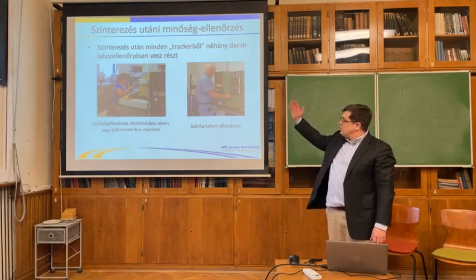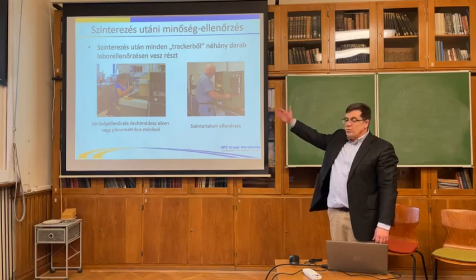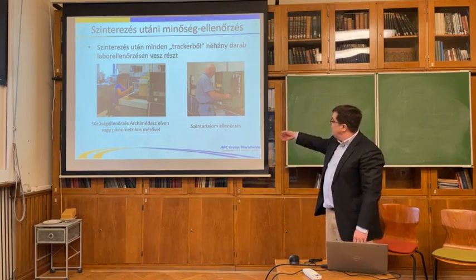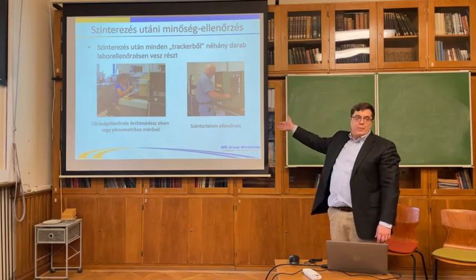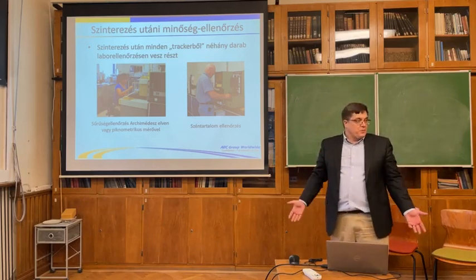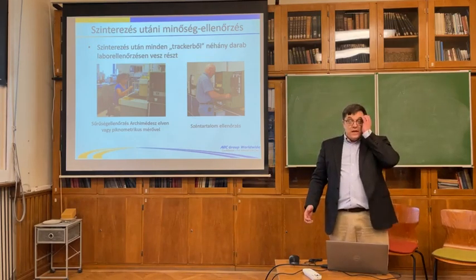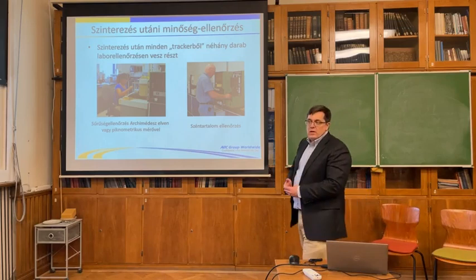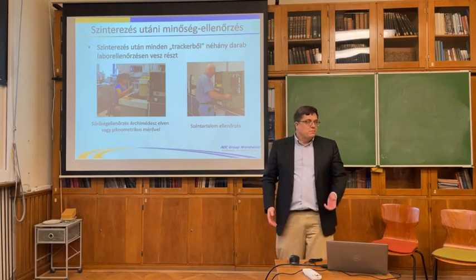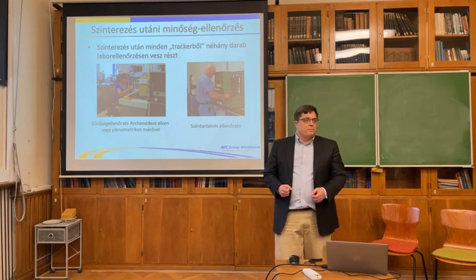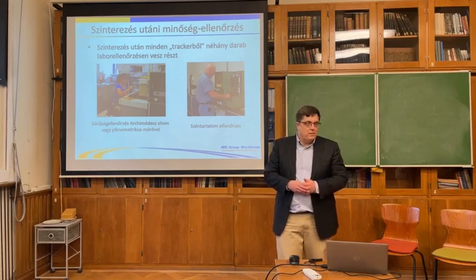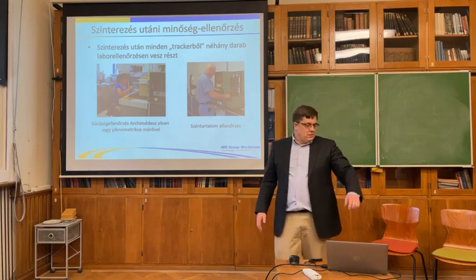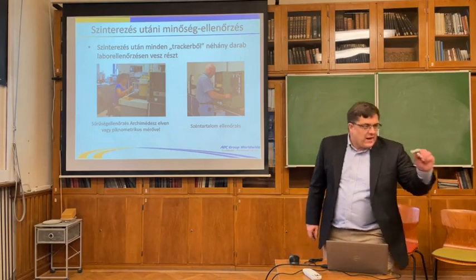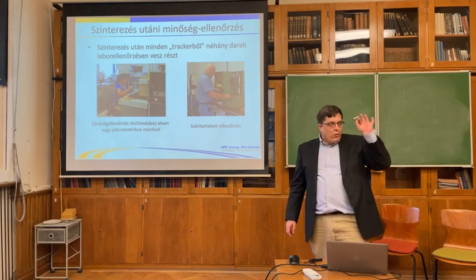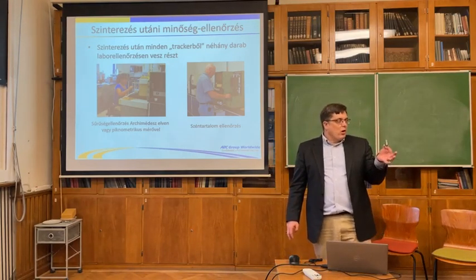So after the sintering, we measure the density through the Archimedes principle or pycnometry, and we always measure the carbon content. If it's steel, you need a certain percentage of carbon, as stated in the ISO or the Metal Powder Industries spec. Usually it's about 0.3%, and for stainless steel, max 0.07, usually about 0.04. So actually a pretty low carbon.